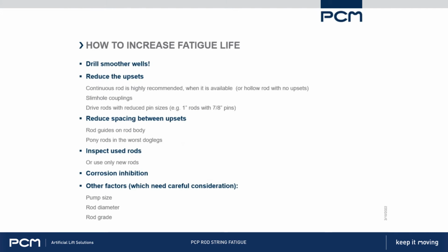If you're using rods that are specifically made for PCP applications, the drive rods, or they have different names depending on who you're buying them from, they often come with a reduced pin size. So for example, you can buy 1-inch rods with 7/8 inch pins on the end. So now you can use a 7/8 slim hole coupling on there, and you get a much reduced upset compared to a 1-inch full size coupling with the rod being the same. That's a very effective product that's been used for a long time in Canada.